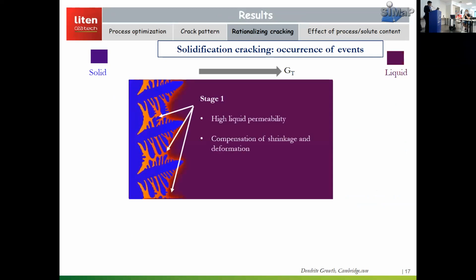So at a particular stage, we will reach a first stage, for example, where you will have high liquid permeability, which basically means that the liquid will easily enter into the dendrites and can compensate for the shrinkage and deformation. And most alloys have this issue with shrinkage because the density of solid is greater than the density of liquid. So you have these shrinkage and deformation issues as well.